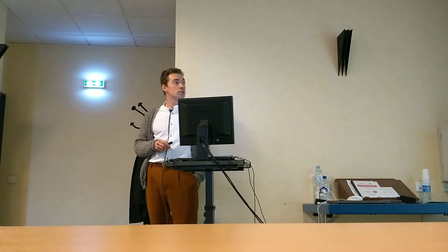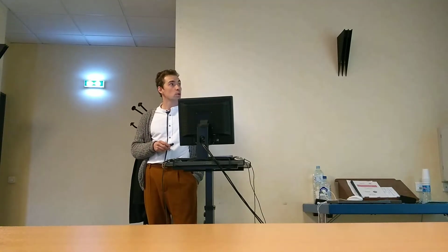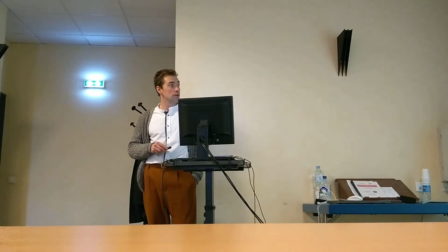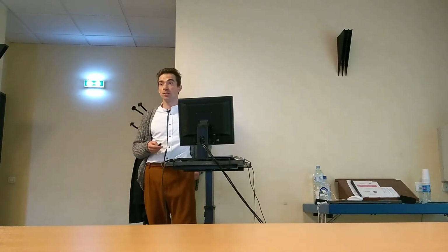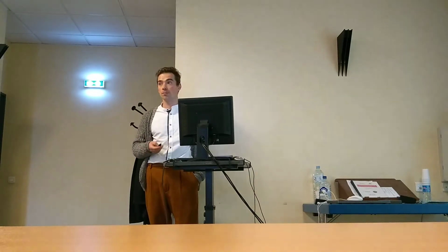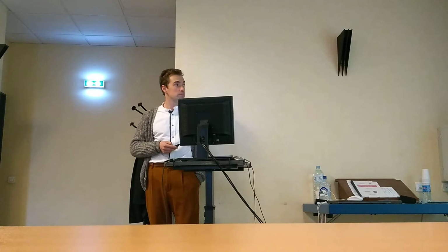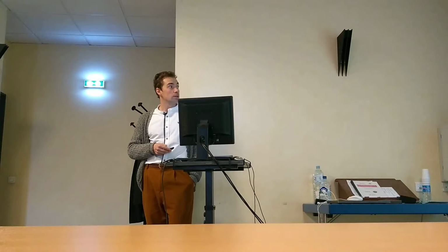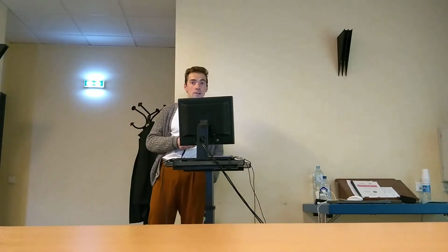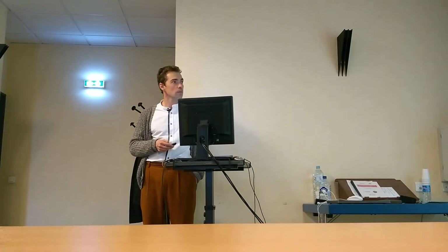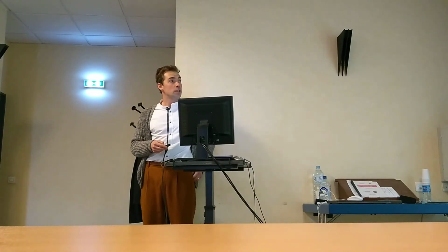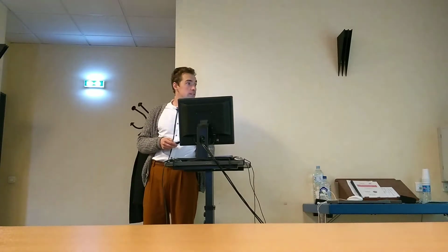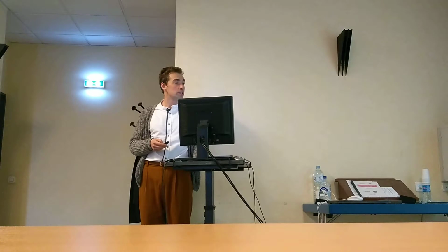So we proposed an alternative model of nanocrystal growth which is based on the real crystallographic faceting of our nanocrystals, as well as crystallographic data which correspond to the material of our nanocrystals. In this case, it's cadmium selenide. So we can see that the typical shape of our nanocrystal is a hexagonal bipyramid, and based on it we built our atomistic model.